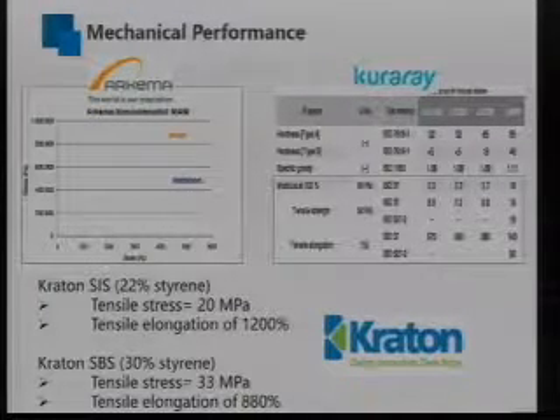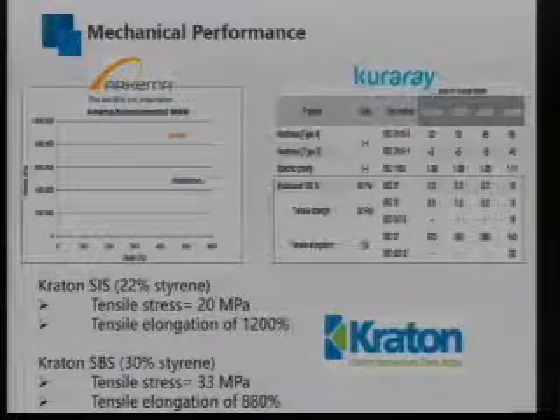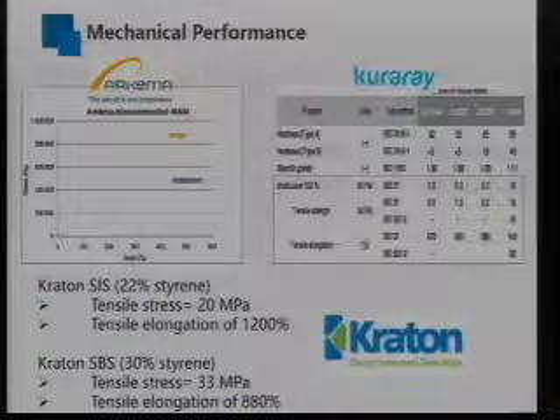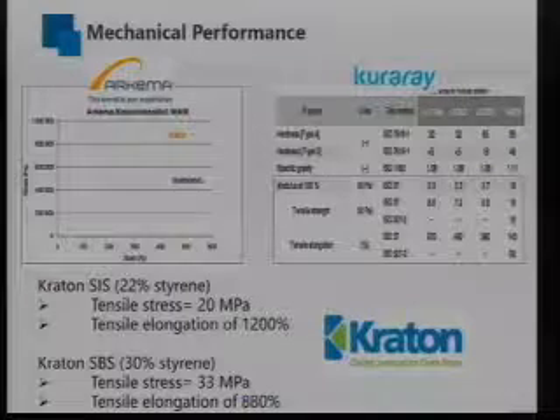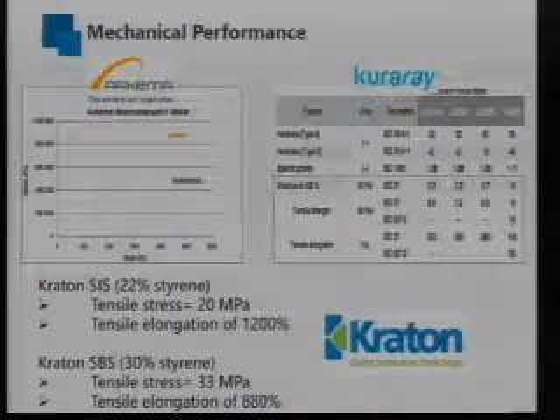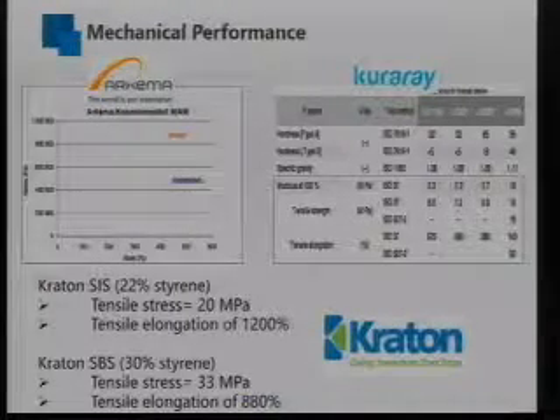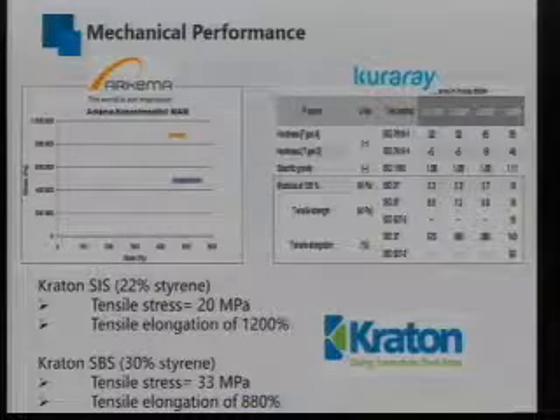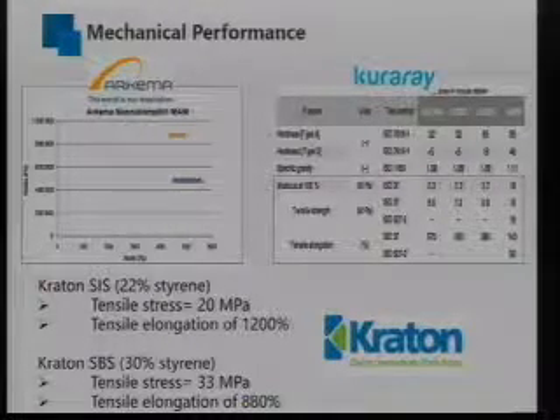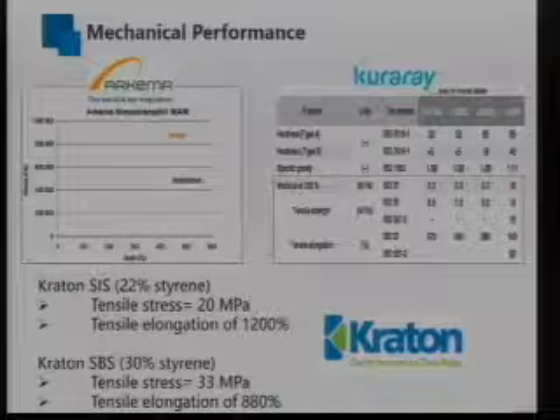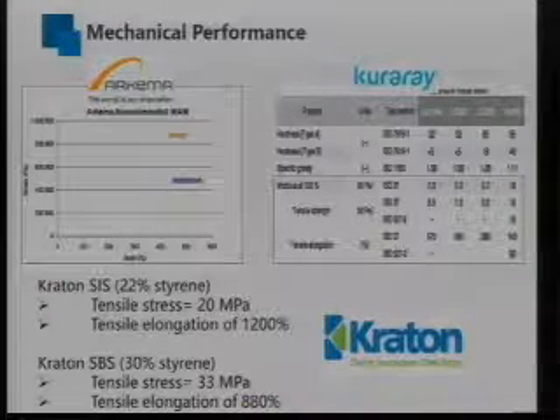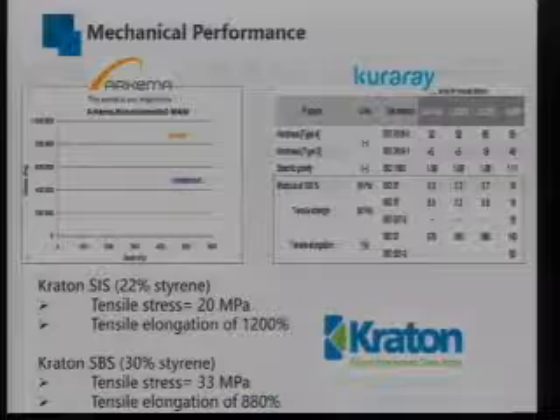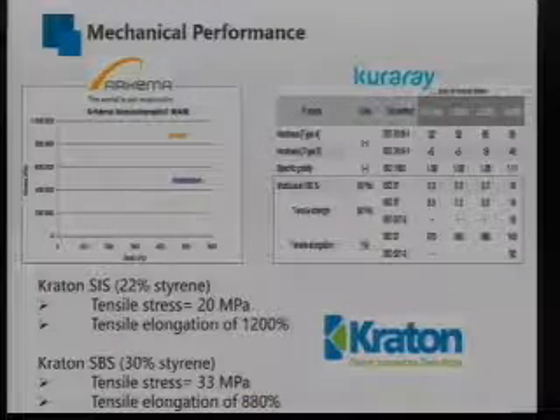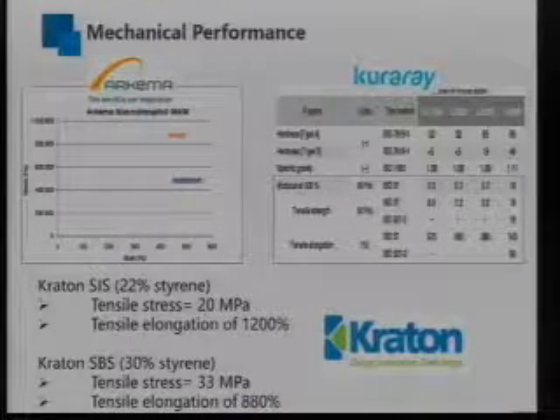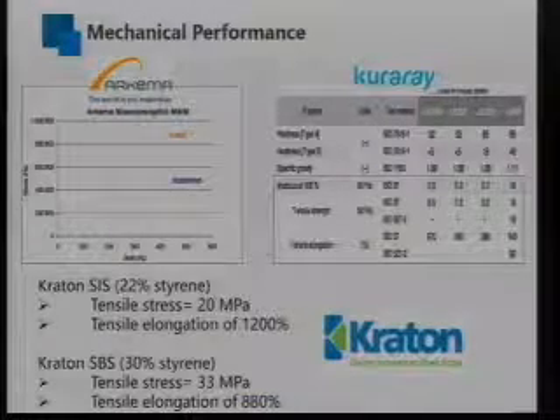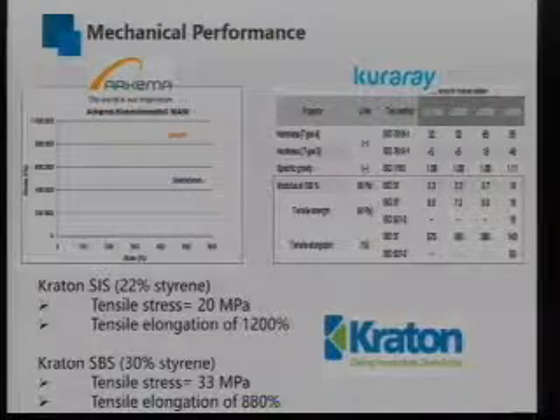In this way, we would rather call this one a plastic instead of an elastomer. And for other products, the elongation is still around or lower than 500%, and the strength is also much lower than the Styrenic thermoplastic elastomers. And for Styrenic thermoplastic elastomers, the elongation can be as high as 1200%, and the mechanical strength can be as high as 33 megapascal. So this is a much larger difference.